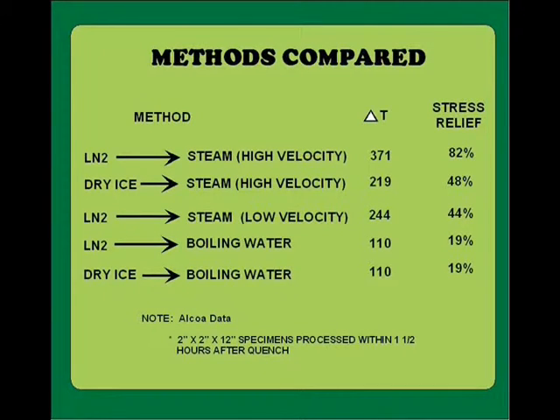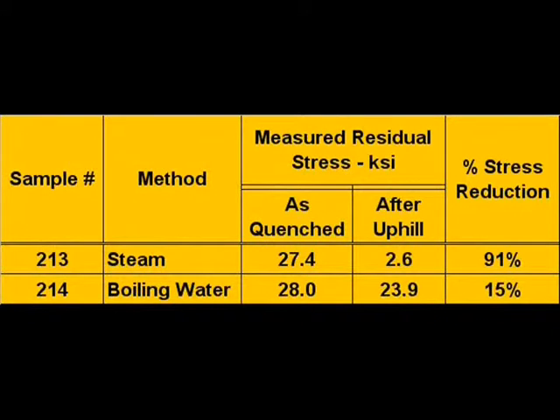It can be seen that when the liquid nitrogen high-velocity steam approach was used, the level of stress relief realized was 82%. However, when boiling water was used instead of the steam, only 19% stress relief was achieved. Work that we performed on a 1-inch aluminum plate confirmed the Alcoa data. High velocity steam produced a 91% reduction in residual quenching stresses, while boiling water only achieved a 15% reduction.